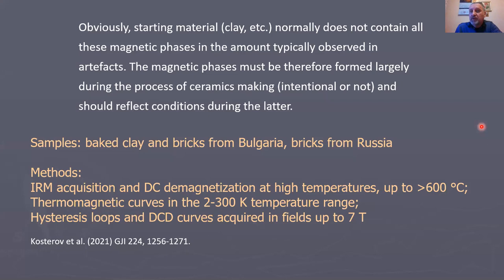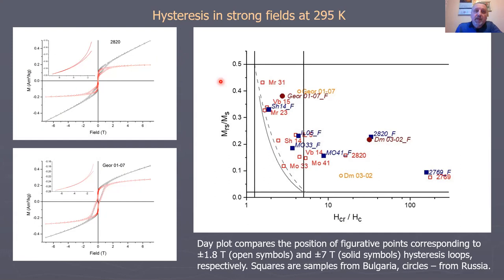Now, briefly to the results. Here you can see the room temperature, seven Tesla hysteresis loops. Raw loops are in black, corrected for high-field slope are in red. And one can immediately see that this hard phase is really hard. We don't saturate the magnetization even in a seven Tesla field, and the loops are open until three or four Tesla.